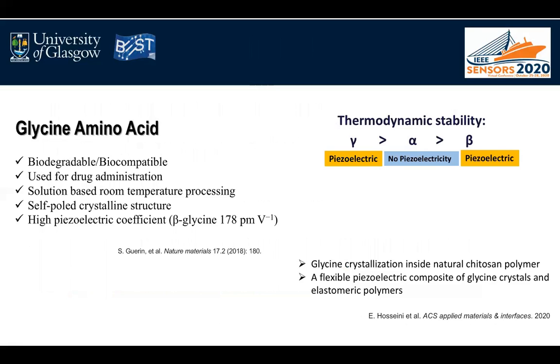Biodegradability of glycine has been well established because it has been used for drug administration, and glycine molecules are able to organize in a self-poled crystalline structure with room temperature solution-based processing, and also it doesn't require a high electric field to induce piezoelectricity in them. And it has a high piezoelectric coefficient in the beta phase and in some specific crystallographic orientations.